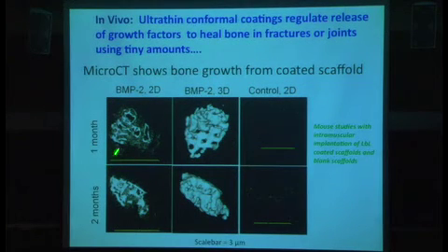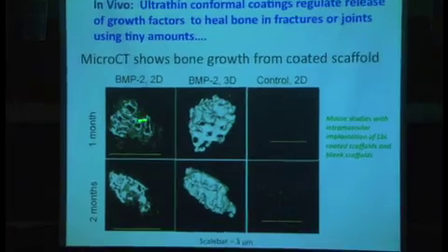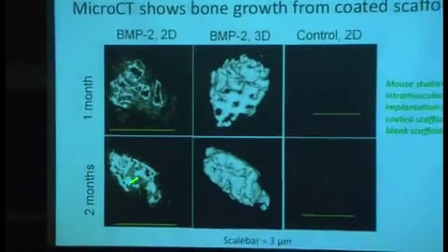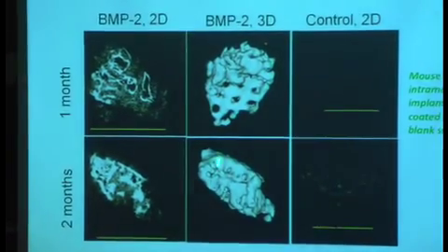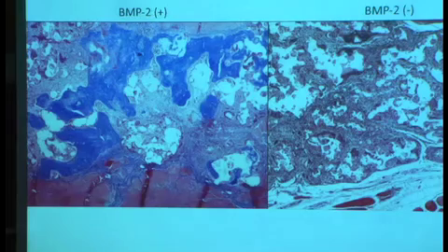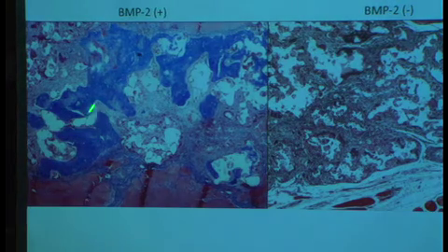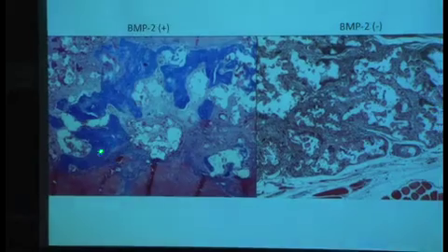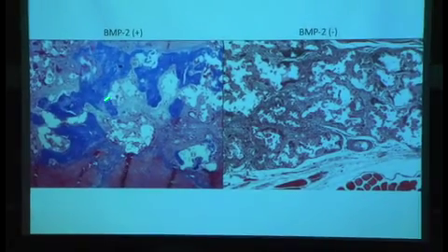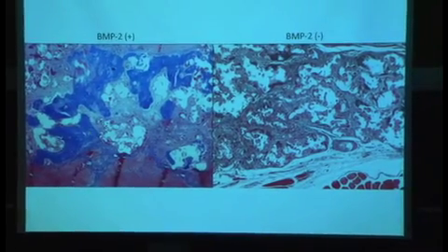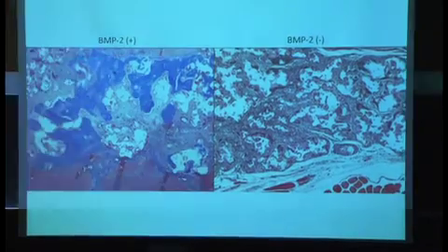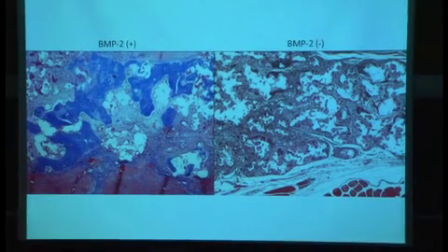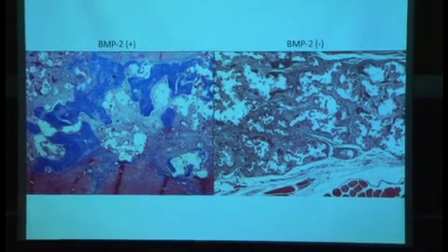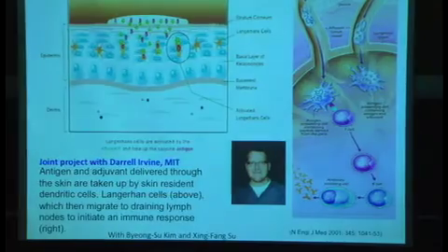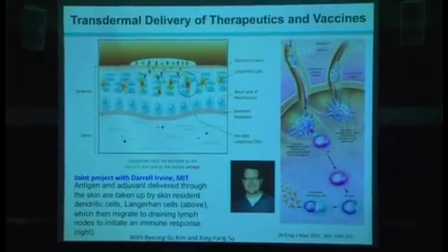We see bone growing. I'm sorry, these are mice. We see bone growing in these systems. We see it densifying, and we see signs of very mature bone. Here, the blue regions are bone, and this is our control, and we see that bone is growing throughout the scaffold. We also see over time the development of spaces which will ultimately become marrow. So we see signs that this is bone that is continuing to mature.